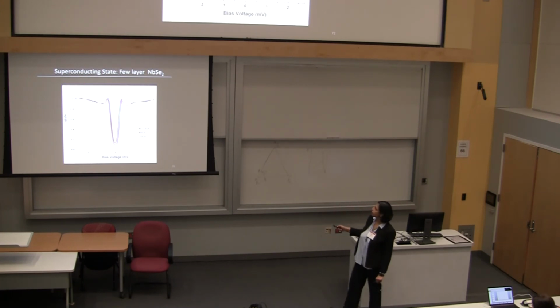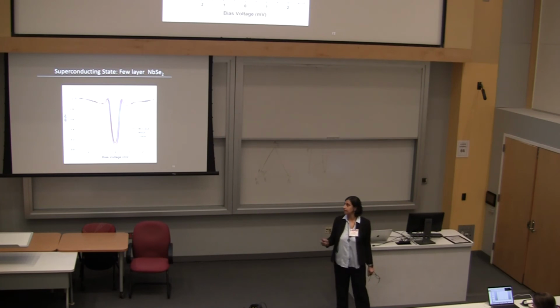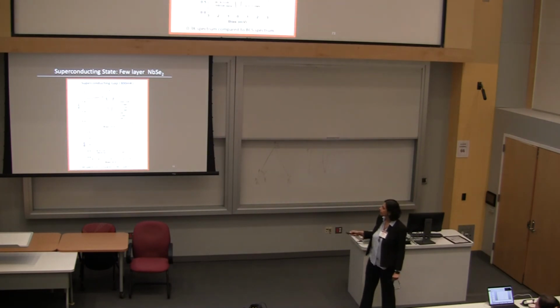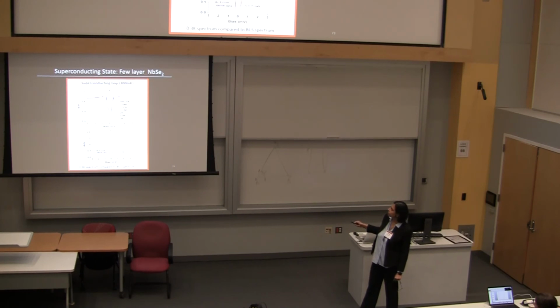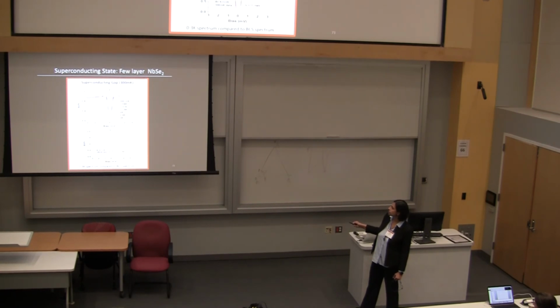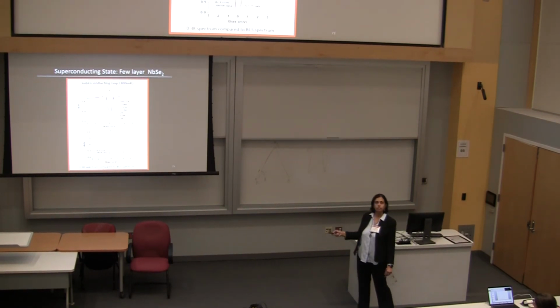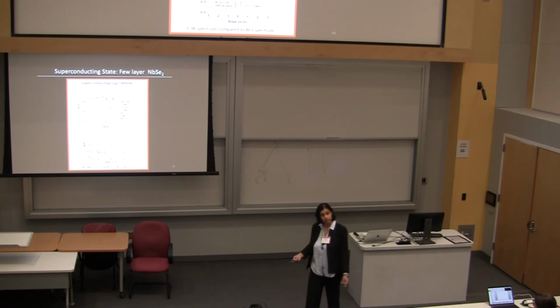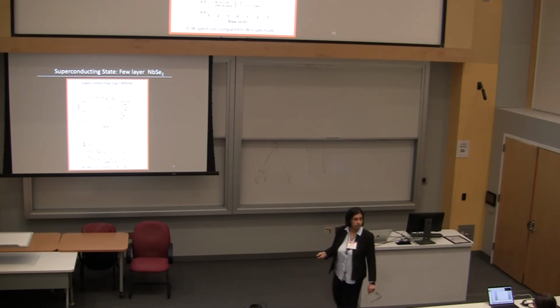It becomes a better and better superconductor as you go from the monolayer to the bilayer to the trilayer. But certainly, even in the monolayer limit, you get a nice superconducting gap with coherence peaks. So this is for the bilayer. If you change temperature, you can watch the superconducting gap go away as a function of temperature. It disappears around 3 Kelvin. So it's a 3 Kelvin superconductor, which is pretty high considering it's just a couple of layers.